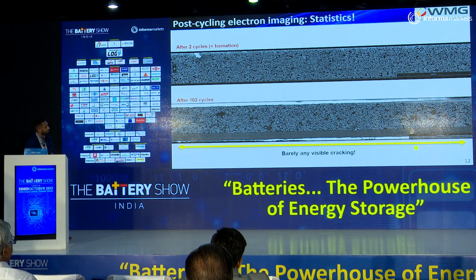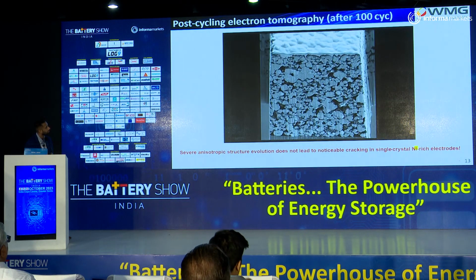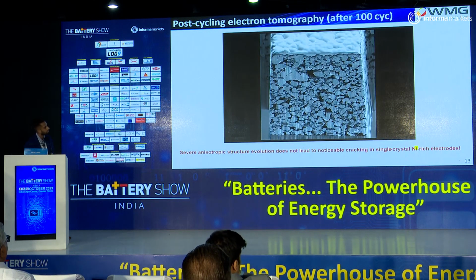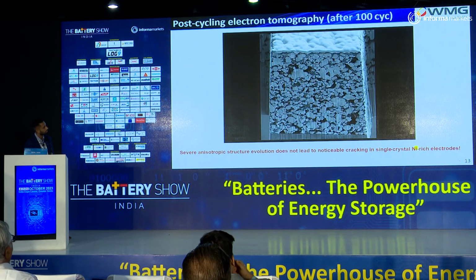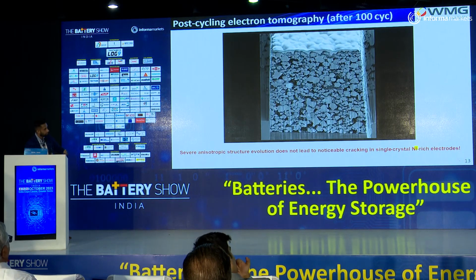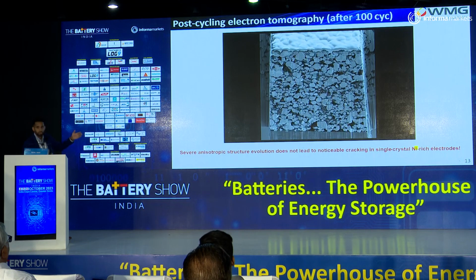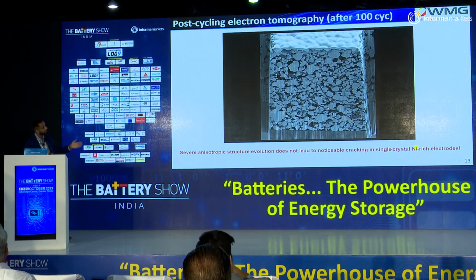cracking within the materials. Now, why do I say this cracking is so important? Well, in polycrystalline material versus the single crystalline material I've demonstrated, cracking induces a larger surface area into our materials, which allows for more degradation pathways in our reaction mechanisms in our cells. So in another publication that we have also presented, this is a cross-sectional image first of the single crystal particle after 102 cycles, and we can see throughout the entire material there is no cracking in any of the material.